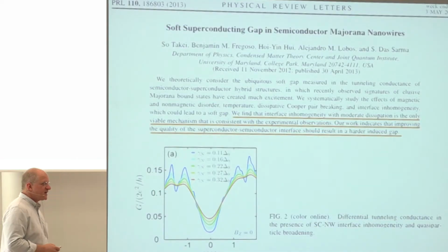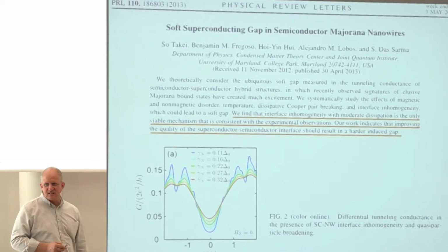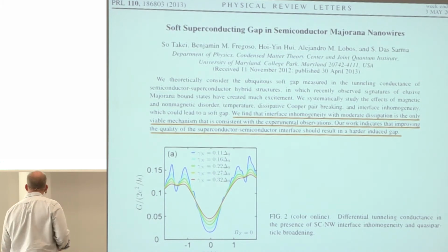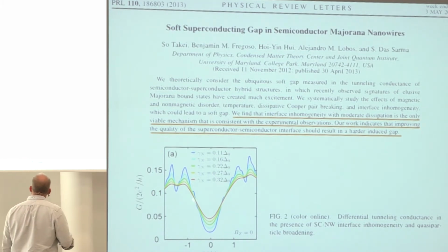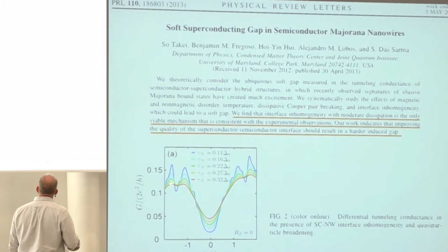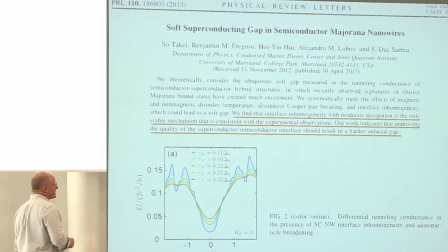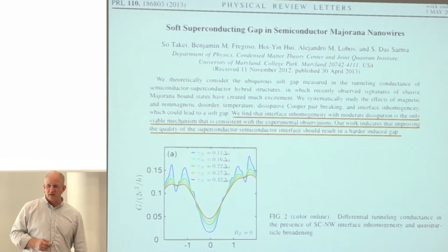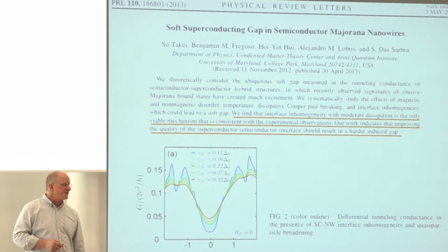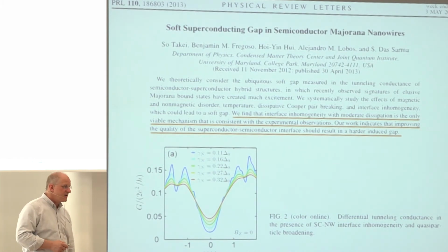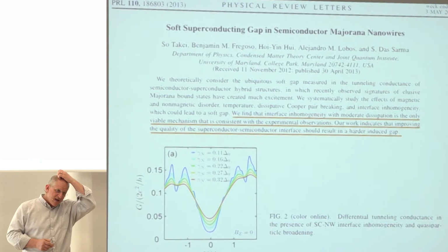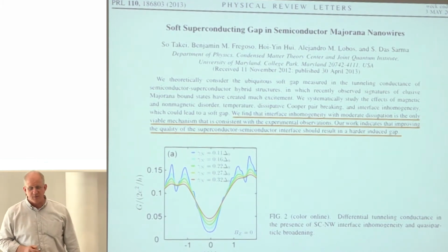I want, for the moment, to turn my attention to another problem, which was, this was supposed to be a tunneling measurement of a BCS density of states below the gap. And what you saw over and over again was like this numerical experiment of something that below the gap looked like this sort of soft valley, and not really anything that you would call a self-respecting density of states of a superconductor. And you can ask, how did that happen, and what does that tell us about the experiment?